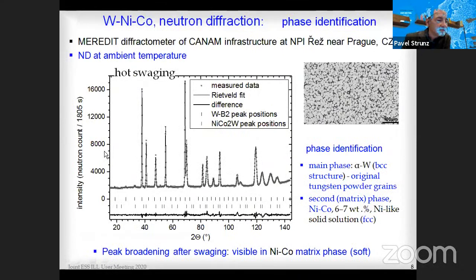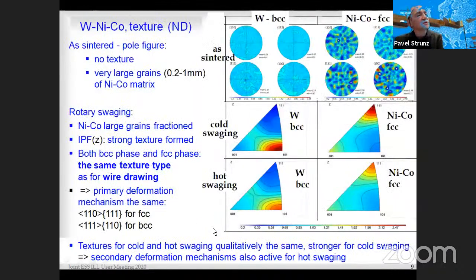So here is shown one of the measured diffractograms at ambient temperature. First, it helped to identify the phases. The main phase is in fact tungsten, original powder grains. But the second phase that is also present, this is in fact the matrix, and this is a nickel cobalt phase, a nickel-like solid solution of FCC structure. There is some visible peak broadening for the matrix phase, but before talking about peak broadening, I will show also the result of texture measurement by neutron diffraction.